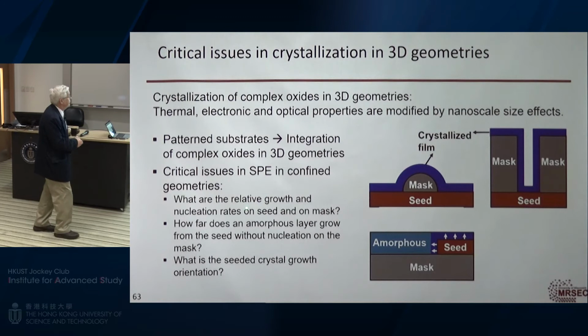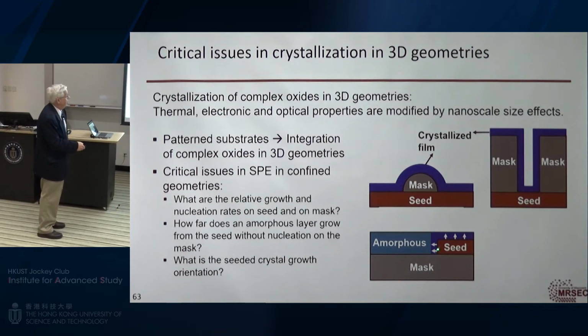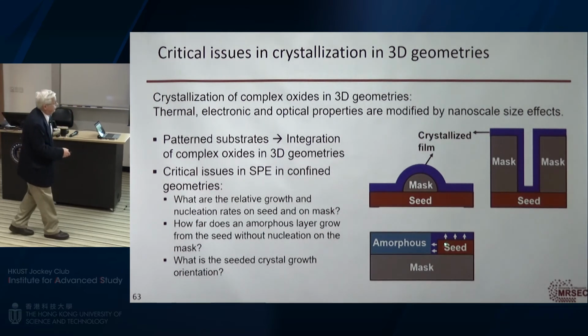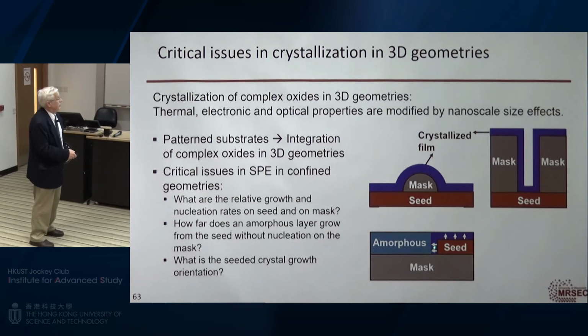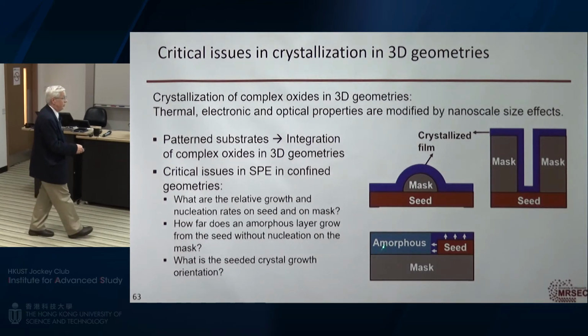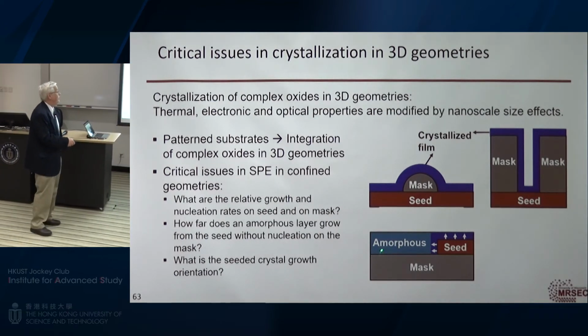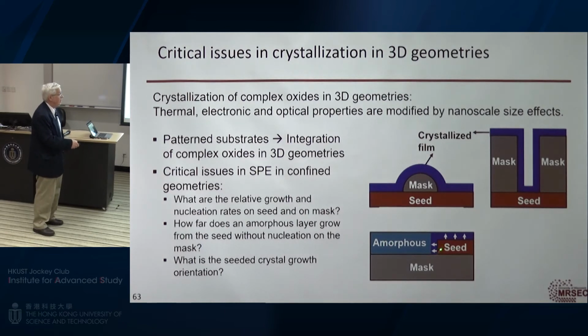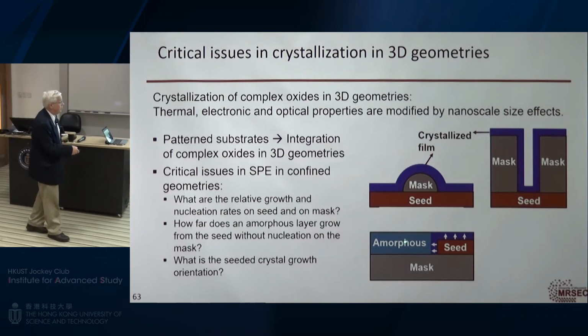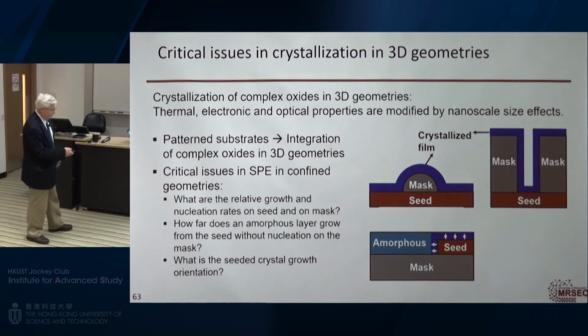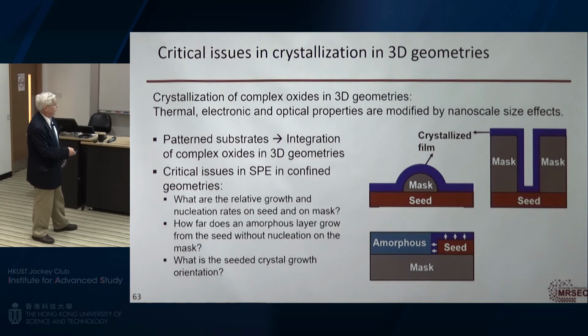And the critical issue is just how fast does it grow off of the seed versus how fast does it start to nucleate a new crystal. So this allows us to do several things. One, the crystallization front is moving through the amorphous material, and if this amorphous material is of a metastable composition that does not want to be thermodynamically stable, it has no kinetic pathway to decompose. And so I can recrystallize and form new types of metastable materials with this solid phase epitaxy.